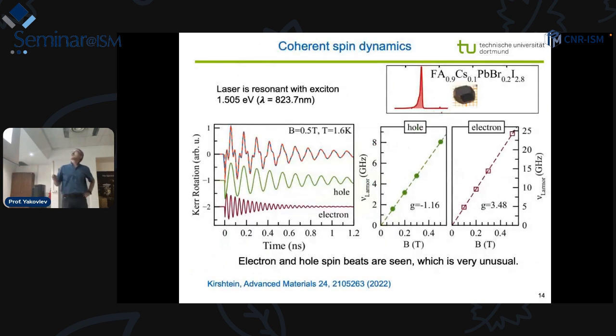So how does it work with the FAPI crystals in the experiment? This is the dynamics which is measured, and typically in such dynamics one can observe one precession signal. But here you see that in the experimental signal, two precession frequencies are present. Here they are decomposed into the hole and the electron precession frequencies.